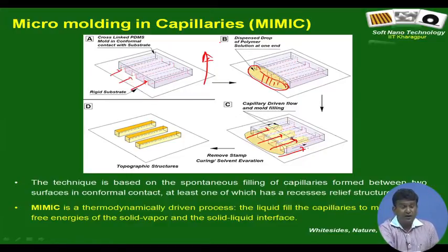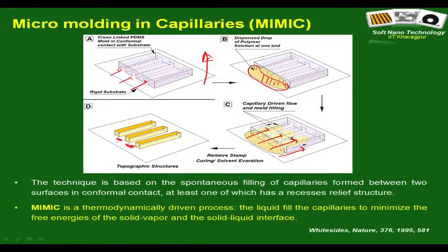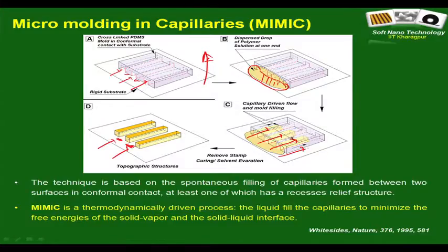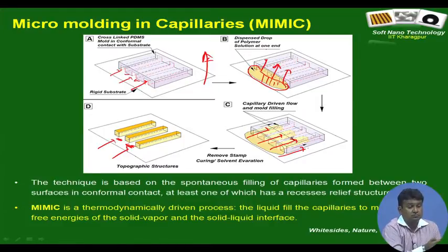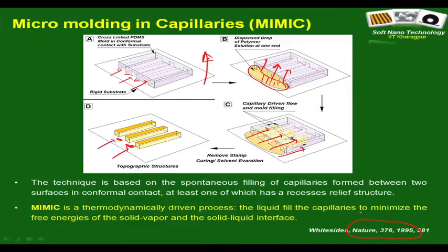Also, if you look very carefully, this method is straight away microelectronics or IC fabrication compatible, because in principle, if your MIMIC is well executed, it does not leave behind a remnant layer like nano imprint lithography. Why? Because over these areas the stamp was in conformal contact with the substrate, and therefore it did not allow the polymer to get deposited. In reality, this is in fact a problem. Often this liquid leads to some bit of flooding, and there is a buoyancy force that lifts up the whole stamp. So, that is a problem, but in principle you can do that. Again, such a simple technique, originally published in Nature in 1995 by Whitesides.